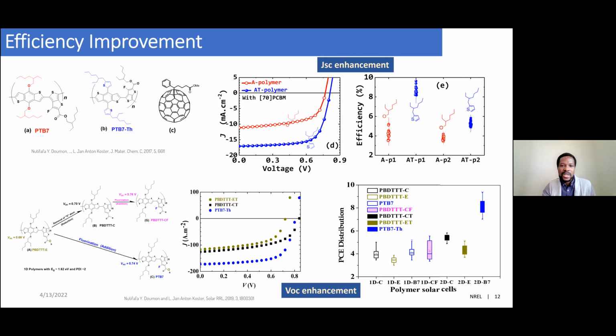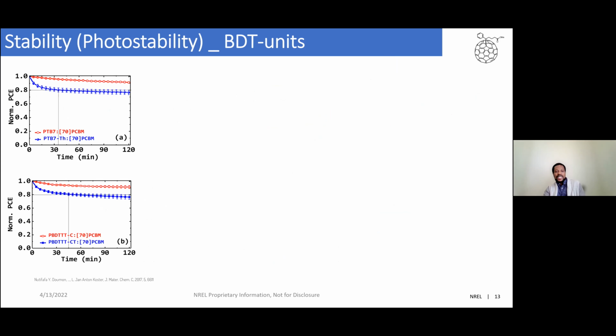Now, when we move to photostability, what you can see is that though the change from the red polymer to the blue polymer was very great for efficiency, that is not the case for stability. You can observe a rapid degradation here under photo-induced stressor for these 2 classes. So you can see it for the first red polymer and the counterpart blue polymer, and then also for the second red polymer and the counterpart blue polymer.